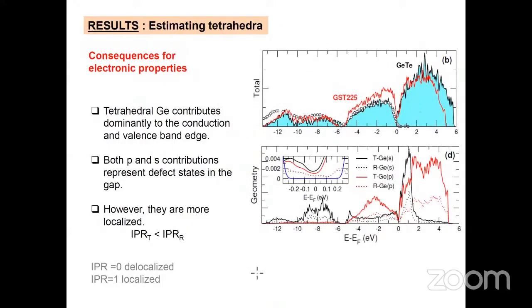So we have some consequences for electronic properties, and I show you just one single figure telling you that actually, having identified those tetrahedral germanium atoms, we're now able to say that they contribute essentially to the conduction and valence band edge, as you can see here. T-Ge is the S band contribution of tetrahedral germanium. T-Ge is the P band contribution of tetrahedral germanium. You can see that both have a dominant contribution around the Fermi level and the gap, and the residue has a much smaller contribution.